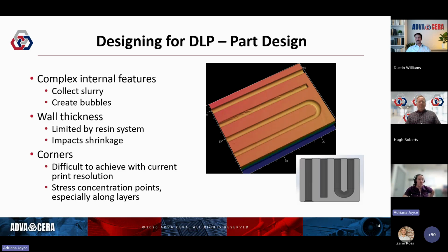Another problem with a feature like this is that if this bottom face is on the build plate of, say, the Lithoz printers, we're creating bubbles because air gets trapped in those channels each time the print comes down, the face contacts the build plate and it lifts back up. We're also limited by wall thickness.